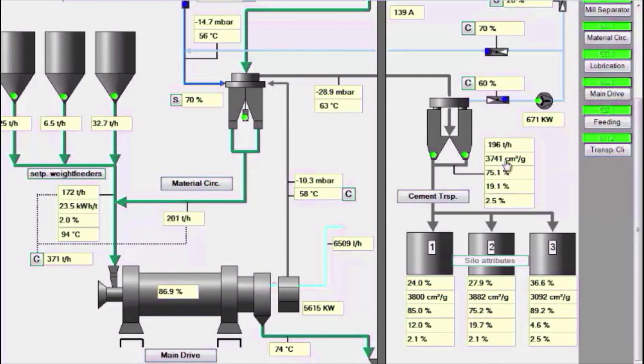Product quality has started to improve, Blaine is already above 3,700, tailings are around 200 tons per hour. Since Blaine is still 3,700 it should be raised a bit. The material level in the mill has started to drop to normal, the default is 75 to 85%. Because the tailings material has started to decrease, we increased the total feeding from 350 to 380 tons per hour, gradually increasing it to 400 tons per hour.